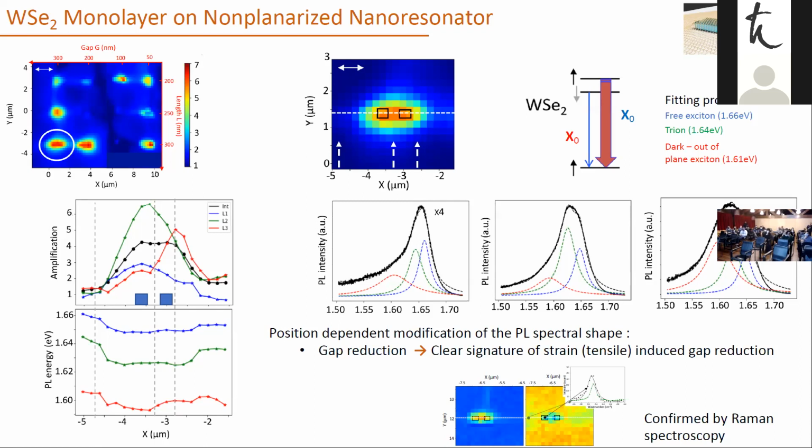Yeah, we tried, but that left a new problem: on the planarized system it's fine, it's very easy, but on a non-planarized system, the antennas are quite high. The antenna height is 100 nanometers. So we have some artifacts when we compare both that come from the fact that the tip is feeling the edge of the antenna before. So we are working on this. Yeah, I'm sure it will reveal a lot of things. Okay, thank you.